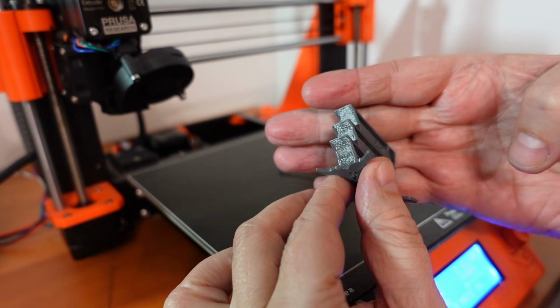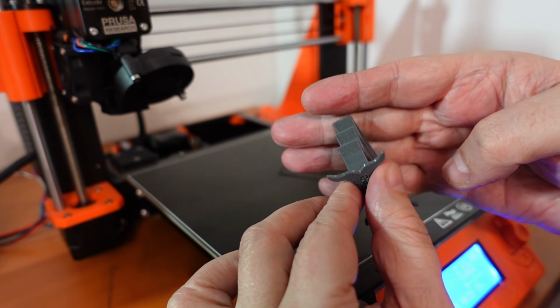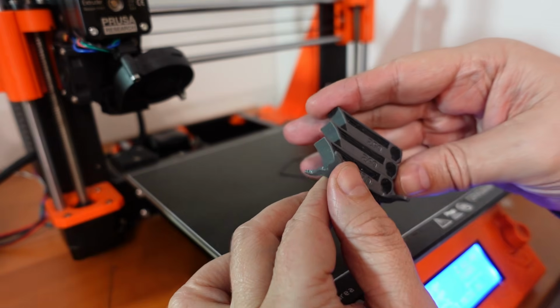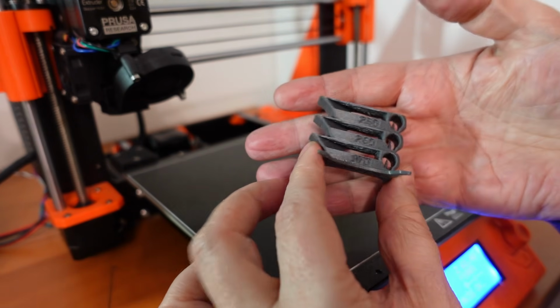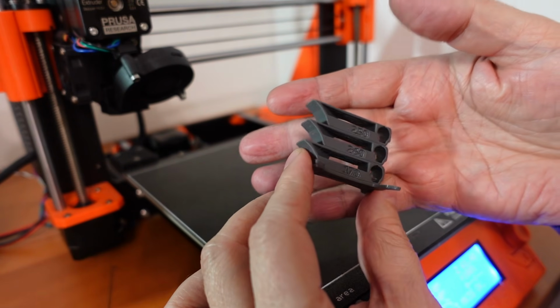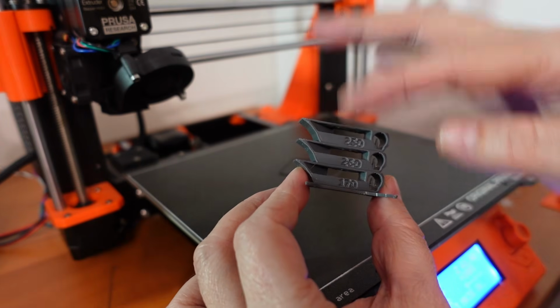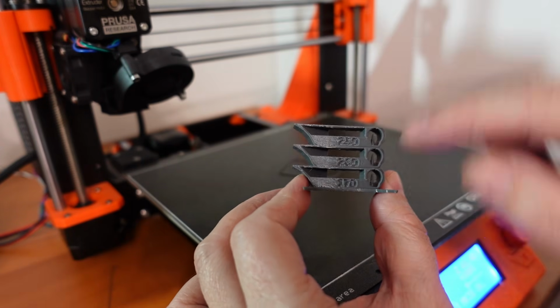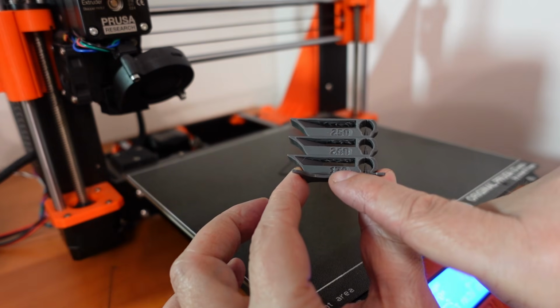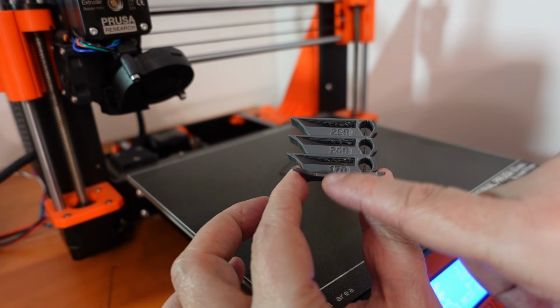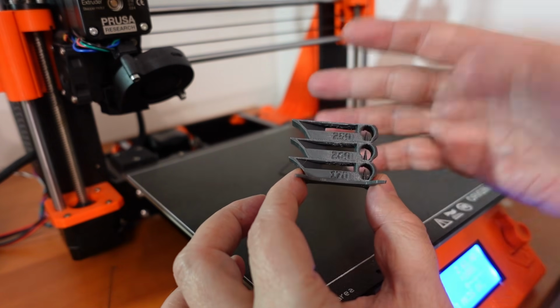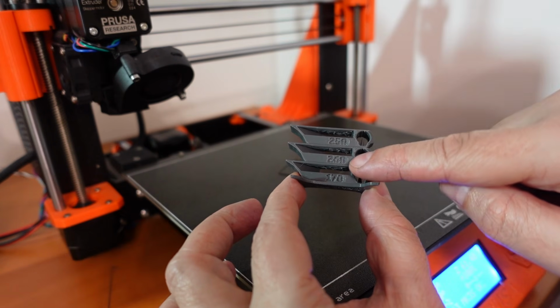And basically like the PETG, this also looks great. This is perfect overhang and absolutely no stringing at any temperature, so basically it is printable on any of these three temperatures. Don't be confused, this is 270 degrees, but I don't have that type of element. And test specimens will be printed at 260 degrees Celsius.